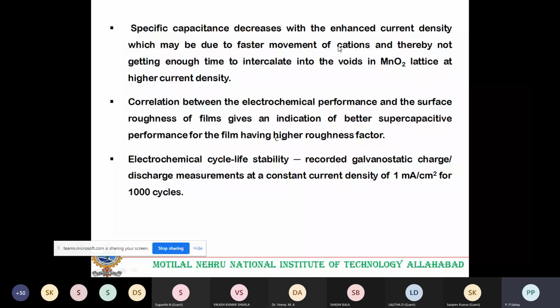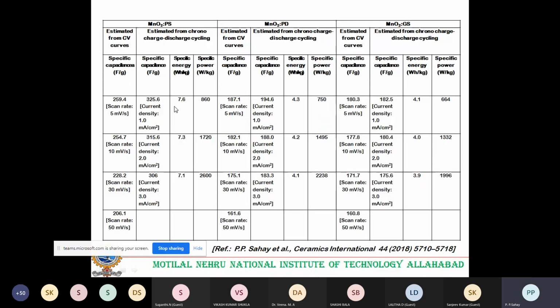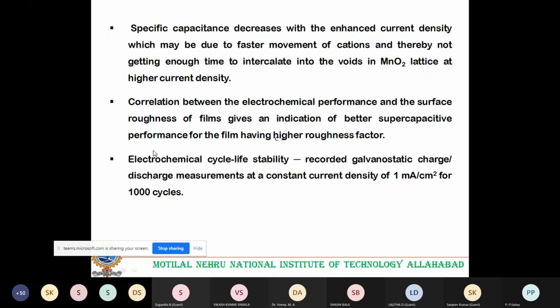So these are the normal inferences. Specific capacitance decreases with the enhanced current density. This is the inference which we have taken from galvanostatic charge discharge. It may be due to faster movement of cations and thereby not getting enough time to intercalate to the voids in the MnO2 lattice at higher current densities. So in the table, we have calculated current density 1, current density 2, current density 3. The specific capacitance is decreasing. Why so? Because here the ions do not get enough time to intercalate into the voids of the MnO2 lattice.